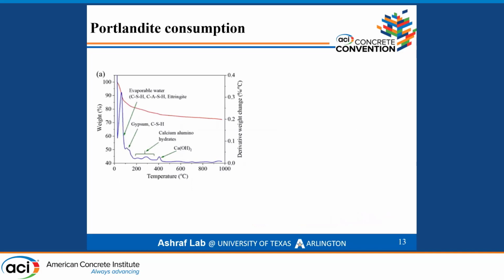For determining Portlandite consumption, we used thermogravimetric analysis. This is a typical TGA plot of calcined clay Portlandite binder cured in seawater. The red line represents the weight loss over temperature, and the blue line is the derivative of that. As you can see, at lower temperatures, the evaporable water, ettringite, gypsum, these kinds of phases decomposed. At around 200 to 350 degrees Celsius, calcium aluminohydrates decomposed, and around 400 to 600 degrees Celsius, Portlandite decomposed.